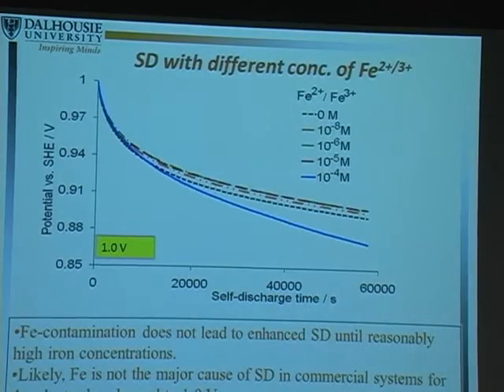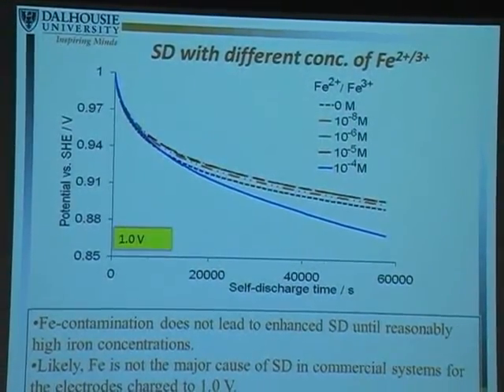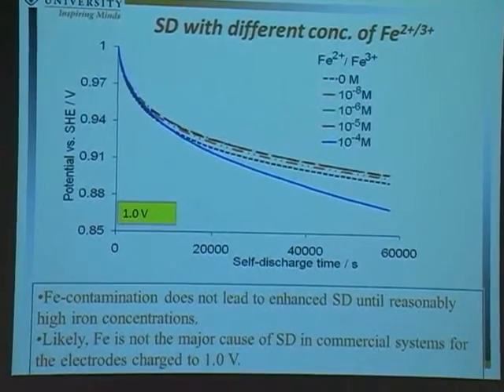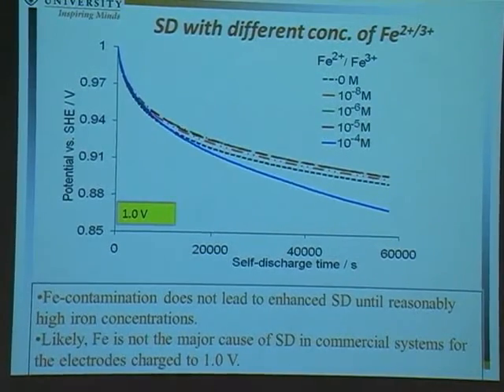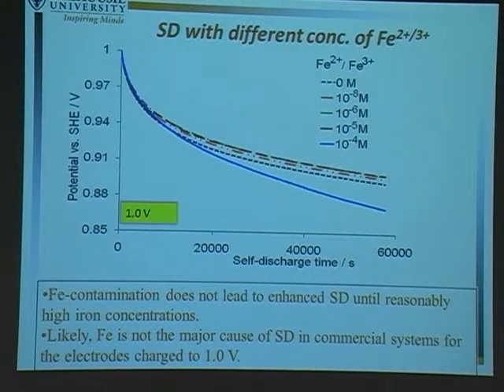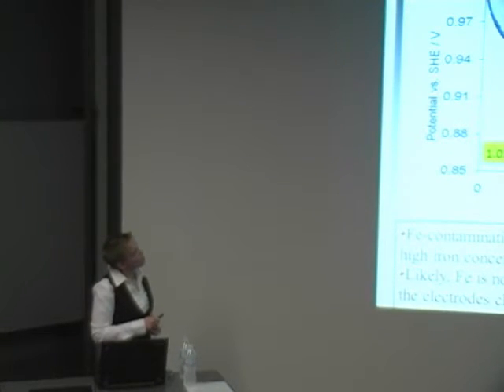And so the way we decided to do this experiment was really very, very simple. We just took our system, we made sure it was super clean, there's no iron in these systems at all, and then we contaminated it with iron. So we started with a very, very pure sulfuric acid. We also took our carbon cloth, which likely has some iron contamination. We cycled it for 350 cycles in sulfuric acid. Then we took that out, washed it, and put it in new electrolyte. We have shown that in that process, we get rid of all the iron. So the self-discharge profile in that situation where there's no iron is shown in black. And then we just contaminated the cell with known amounts of iron.